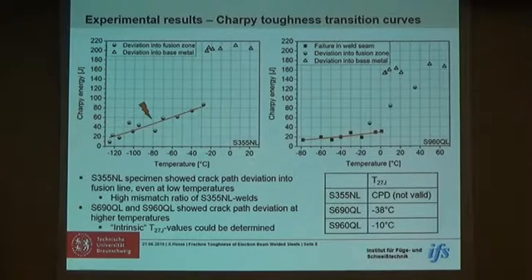If we have a look at the experimental results for the Charpy toughness transition curves, it occurred that we weren't able to detect the brittle fracture within the weld seam for the S355 welds. We saw crack path deviation into the fusion zone even at relatively low temperatures. In case of the S690 and S960 metals, we were able to determine failure in the weld seam itself. So we can speak of an intrinsic T27 value that could be determined.